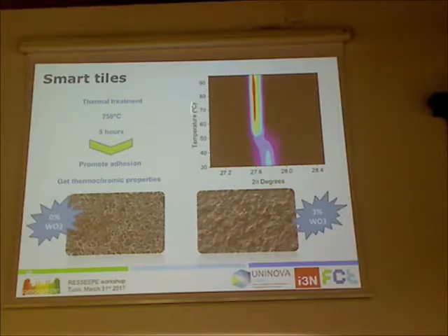If you make the temperature analysis after this treatment and start to heat up your tile, you see the transition. This should be the X-ray diffraction pattern, showing the reflection maximum for the monoclinic crystallite structure. Around 45 degrees, the reflection changes to a different angle, meaning you have a modification in the crystalline structure. So you now have the tetragonal structure—that's the thermochromic effect. You see the phase change at 45 degrees, as expected for the tungsten oxide.